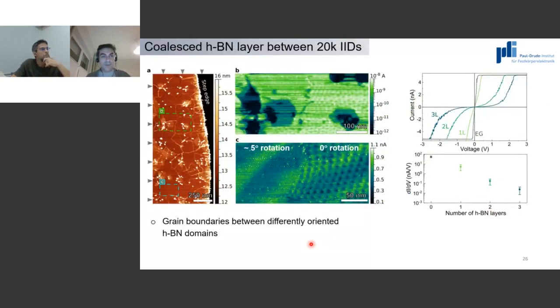now if we grow for a longer time, in order to grow a coalesced HBN layer, this is for the case in between 20,000 ions per IID. Not ideal, but that's what we had at the time. So the arrows here represent the matrix of defects that we are forming. And then we grow for a longer time, and we see that we have merging of the islands until we form a closed layer of HBN. Not ideally a monolayer, but it's at least much better than what I showed you before, the 600 minutes, where we have a lot of out-of-plane growth.